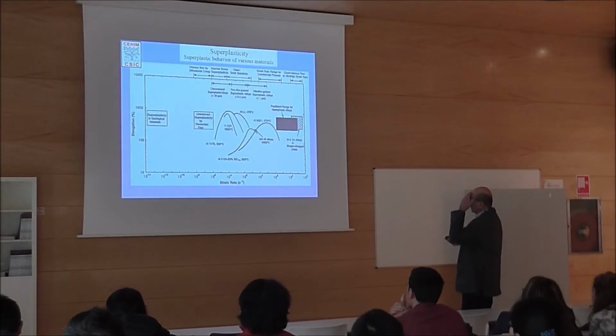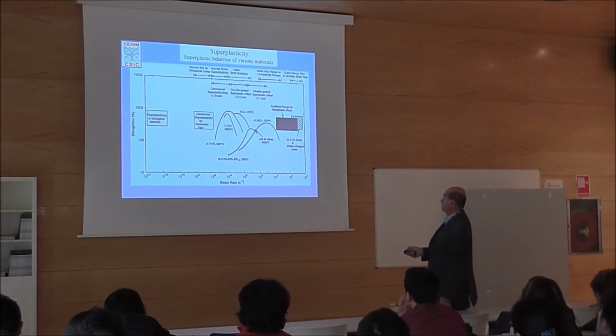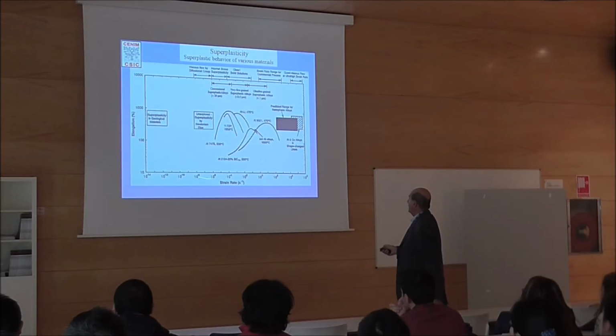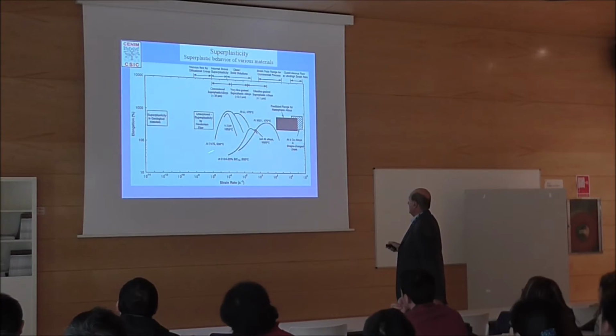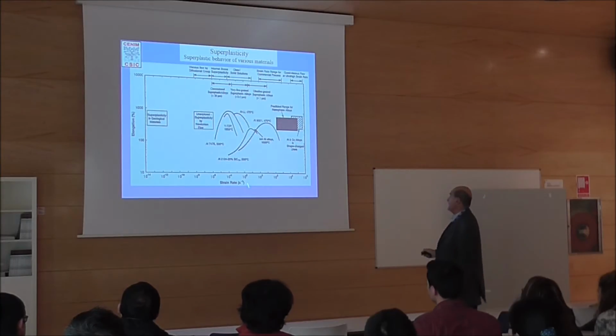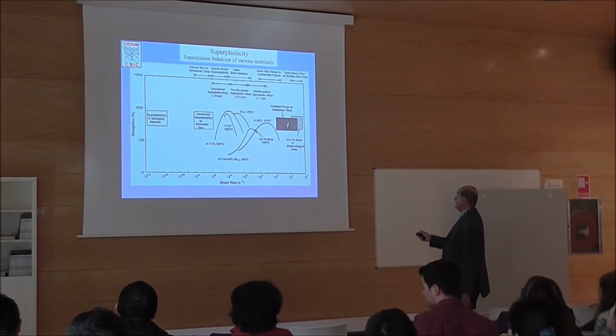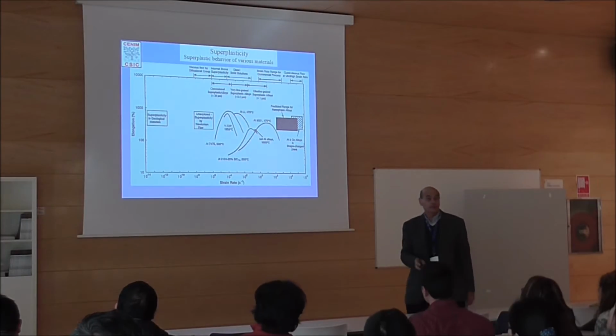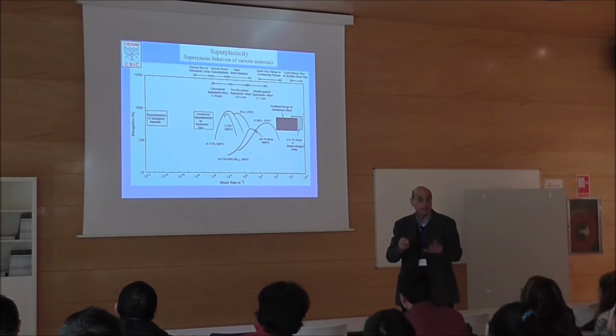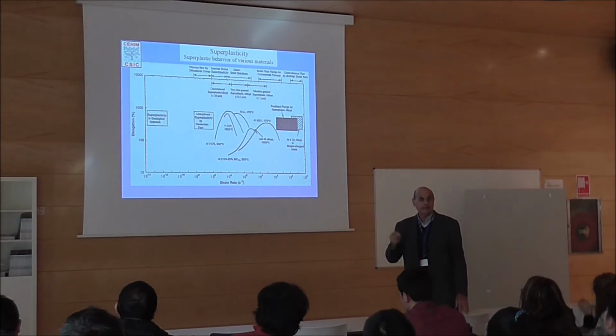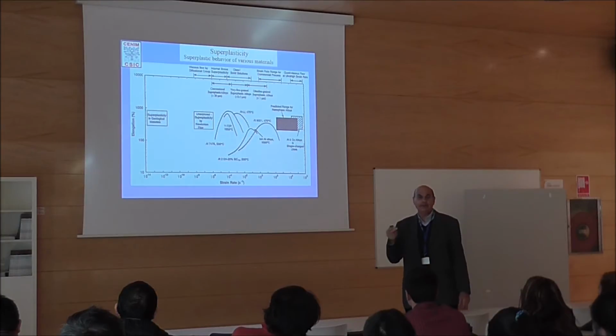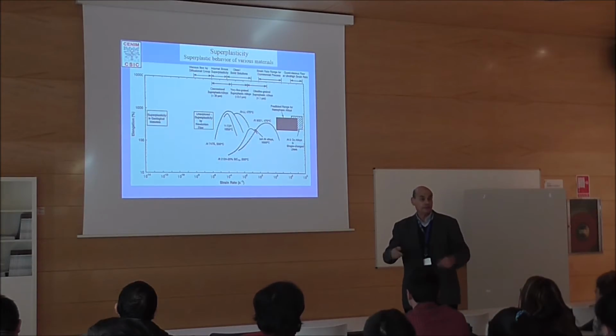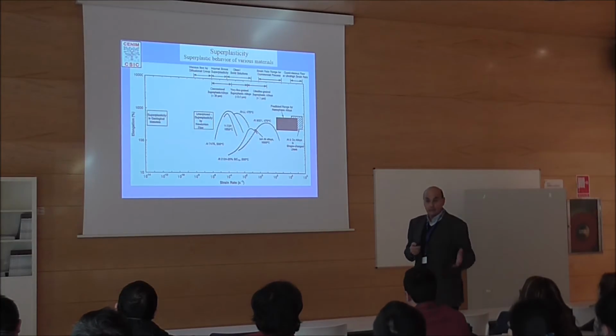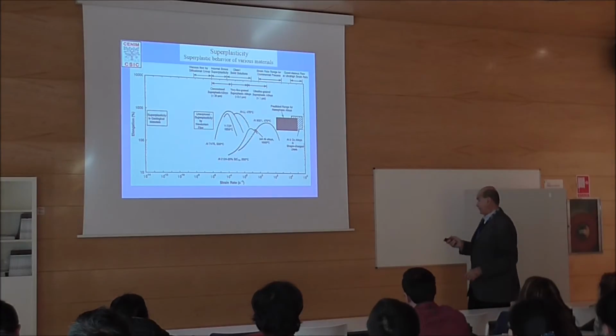Example, and this is not only at these strain rates. If we reduce the grain size, we will have superplasticity even at 10 to the 2. We predict 10 to the 2 per second. And it has to be proved. At least there is high strain rate superplasticity at 10 to the 1. It has been demonstrated, it was published in Nature recently, 5 or 6 years ago.